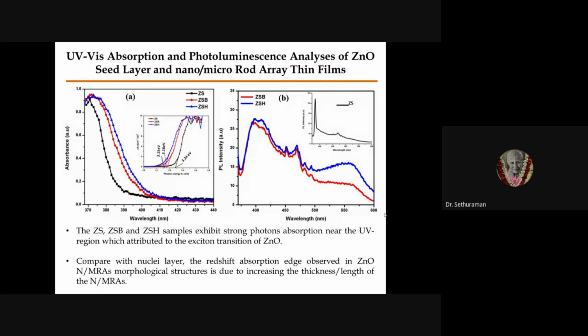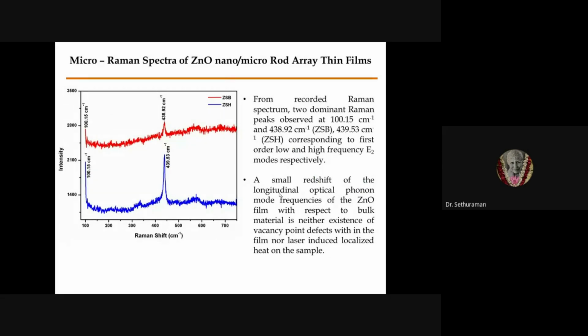From the UV visible absorption, the seed layer, and the chemical bath deposition as well as hydrothermal samples exhibit a strong photon absorption near the UV region, which is attributed to the exciton transition of zinc oxide. Compared with the seed layer, a redshift in absorption is also observed in the zinc oxide nano micro rod morphological structure. This may be due to the increasing thickness as well as length of the nano micro rod arrays. From the micro Raman spectrum, we confirmed the two dominant Raman peaks corresponding to the first order lower as well as the high frequency E2 modes. A smaller redshift is also observed here.